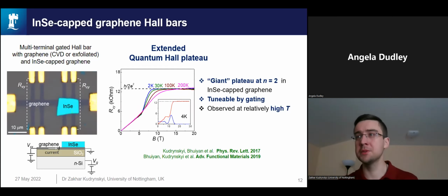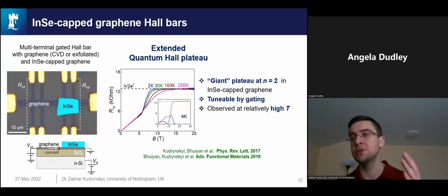And this effect is observed when the Fermi level starts approaching the conduction band and donor band states in the indium selenide. And because of the high density of states, you have a pinning of the level. This extended plateau persists at high temperature. And these states close to the conduction band edge have high binding energy. We measured these donor states in the system, and we measured the binding energy of the order of 30 milli-electron volt.